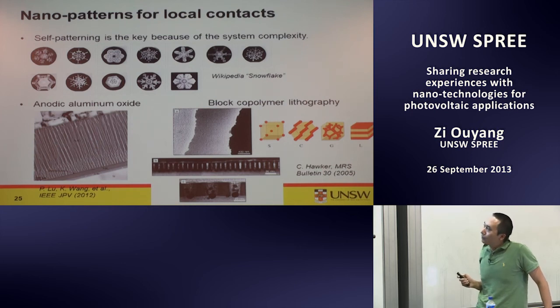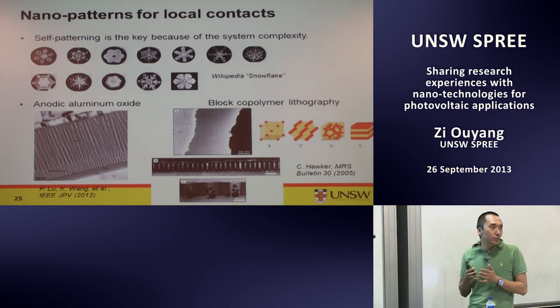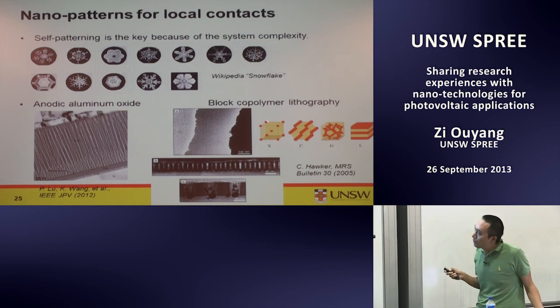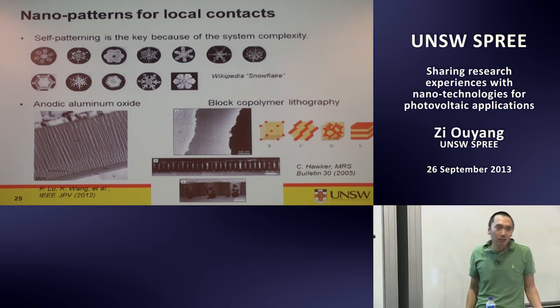Another thing I want to explore is called block copolymer lithography. If you have two polymer materials combined together, these two generate different domains if you control them nicely. In this case, it's just a proportion, and you can have polymer A and polymer B in this shape, and if you increase the composition of polymer B a little bit, you have this, then you have this. If you do it properly, these people have already proved that you can have this kind of porous structure, a very nice film with holes. And people demonstrate they can actually put metal through the holes. So that's another interesting thing to explore.